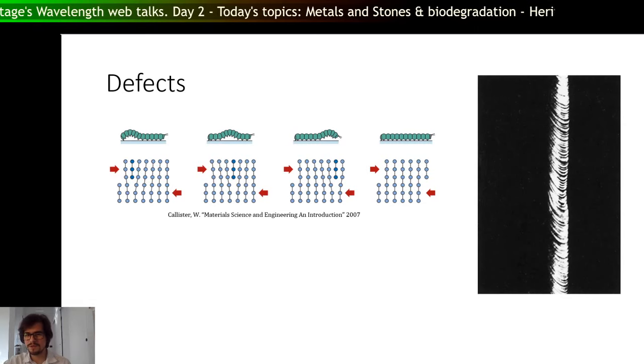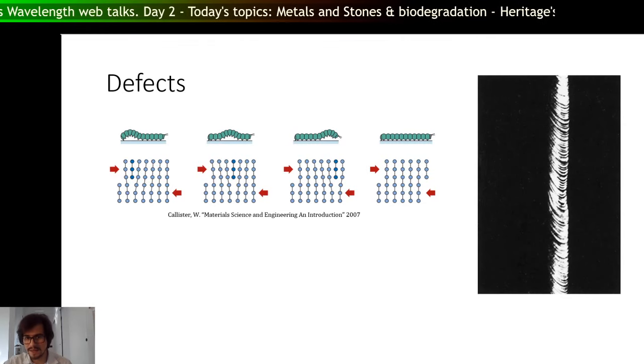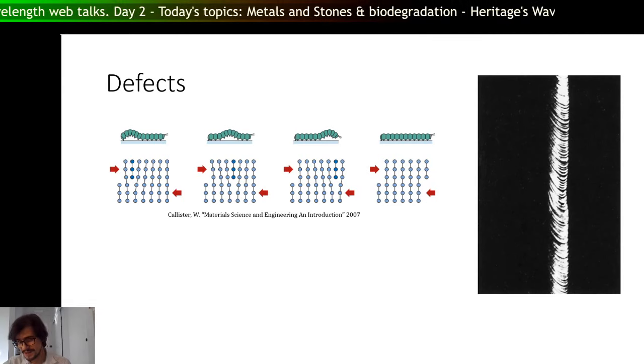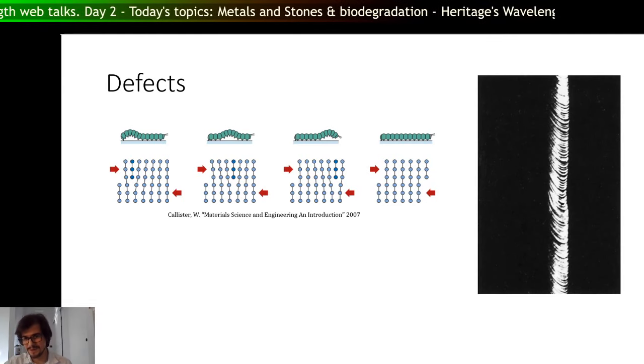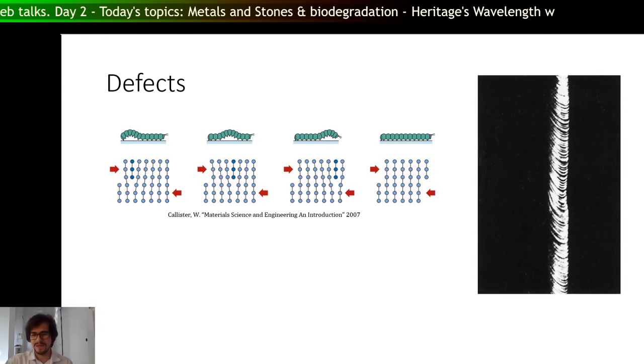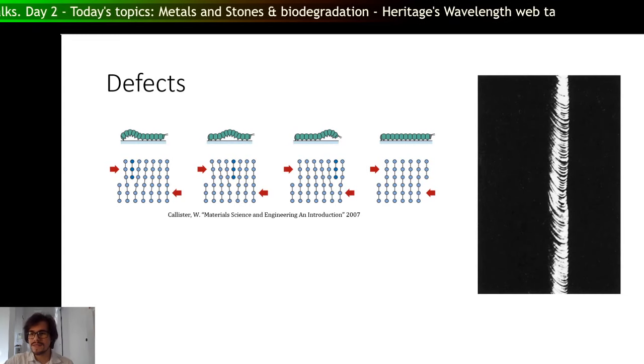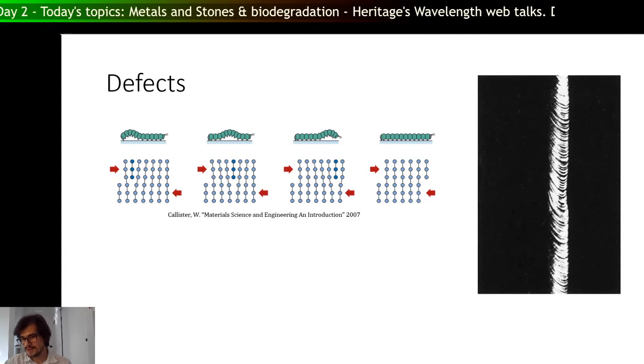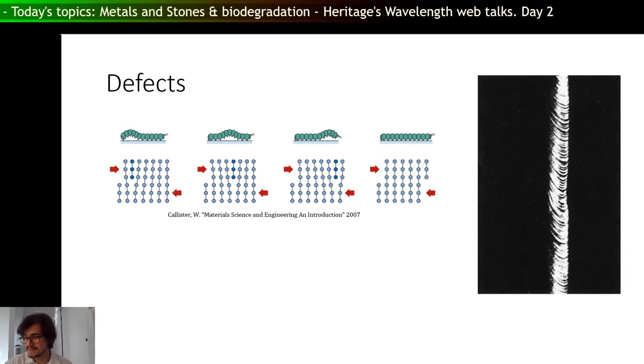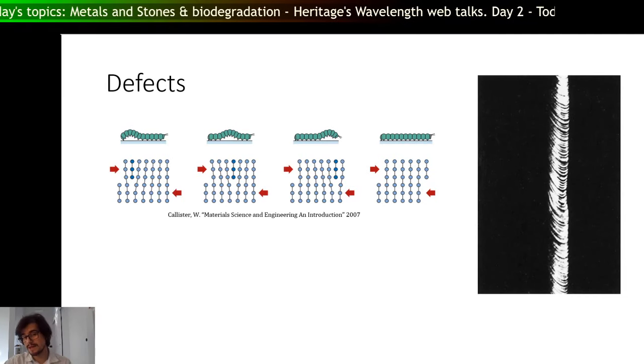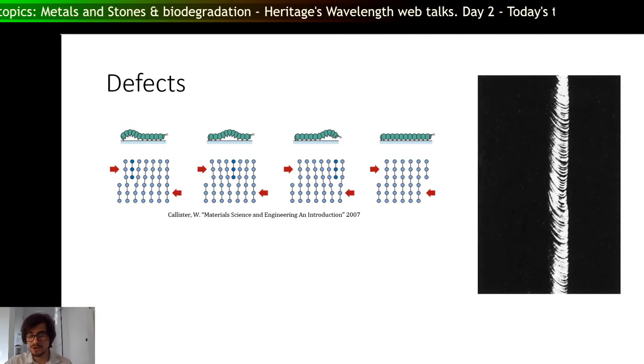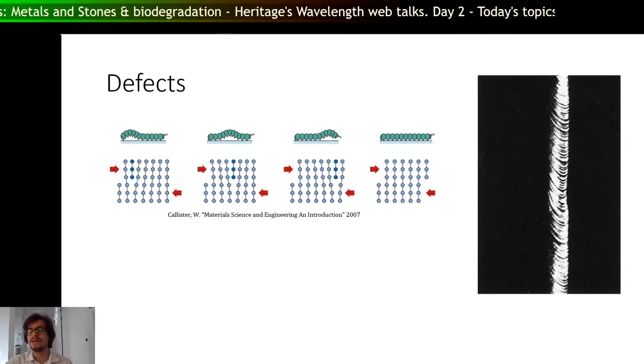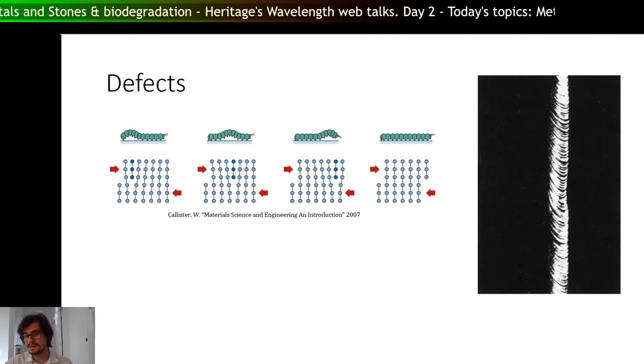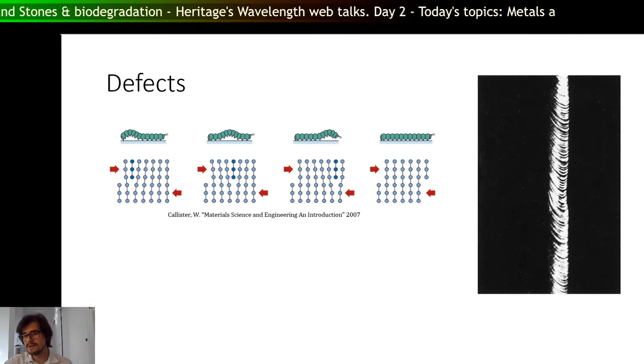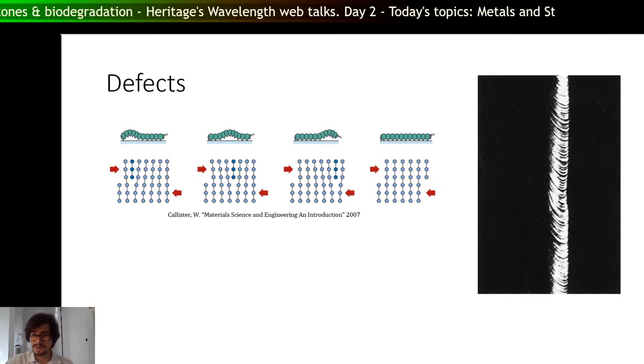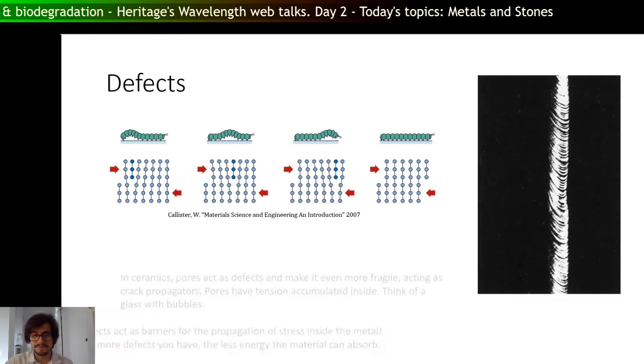If you have a monocrystalline metal, which means it is just one big crystal, you will see bumps on the surface after you apply some stress to it, because the defects inside the matrix propagated. They had no other boundaries to change their direction. They were just moving on since it is just a big crystal, and they reach the outer surface, creating these bumps. Monocrystalline metals and materials do exist.